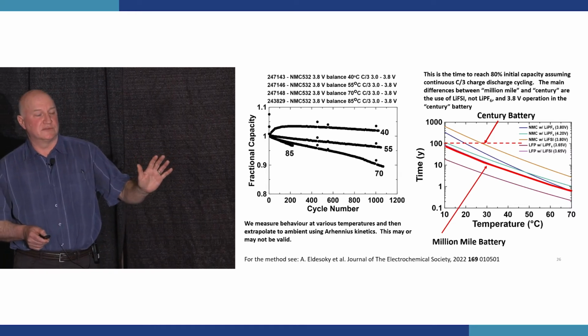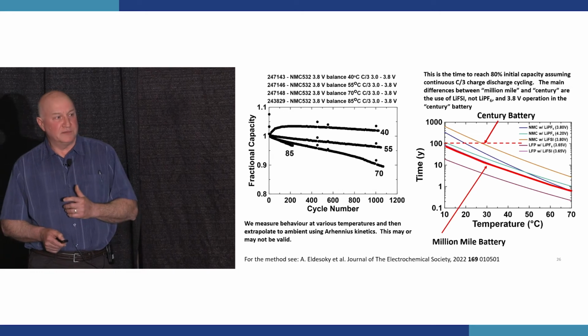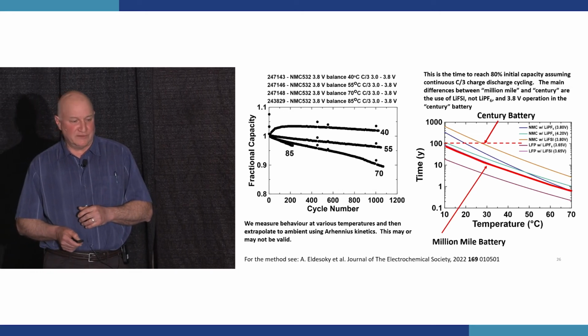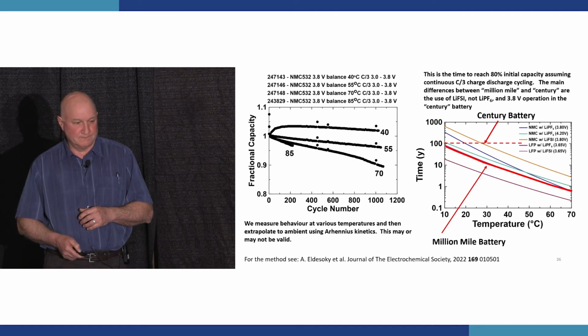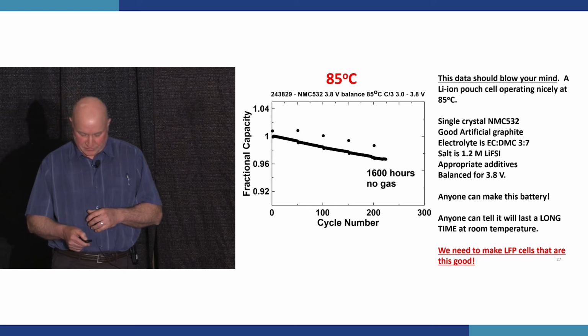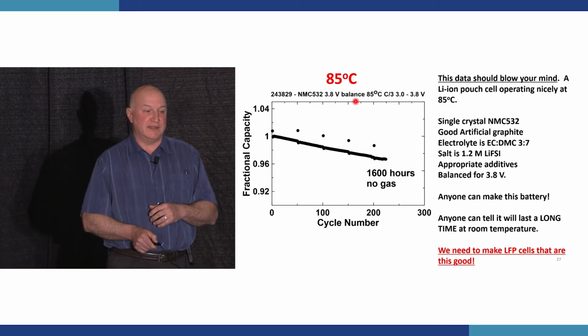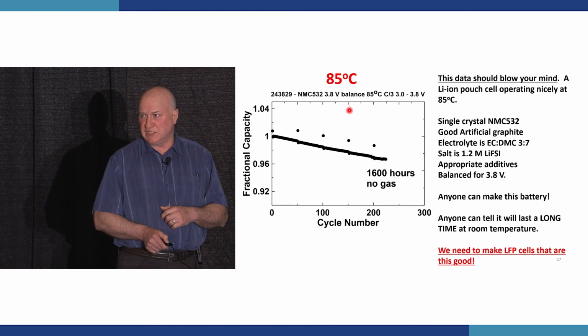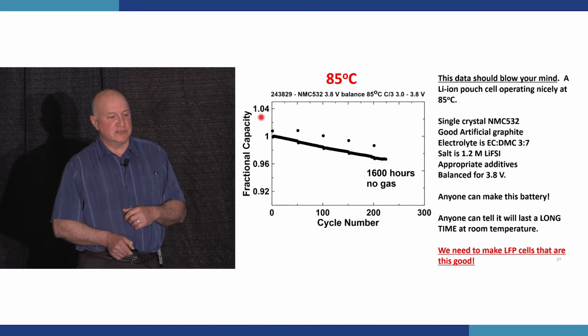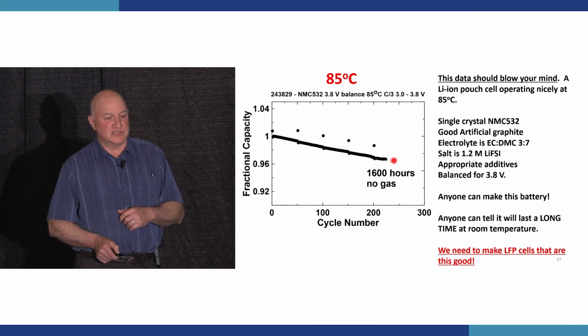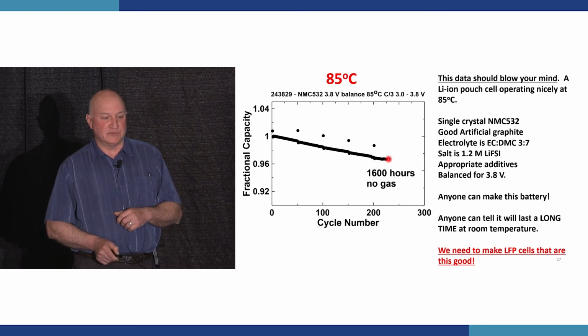Now, if there's lithium-ion people in the audience, and I know there's a lot of you, you'll notice that there's this test data at 85 degrees centigrade over here. I just want to highlight that for your benefit for a second. See that red? 85C, okay? Look at the capacity retention. 1,600 hours of testing at 85C, no gas in these pouch cells at all, 96% capacity retaining.